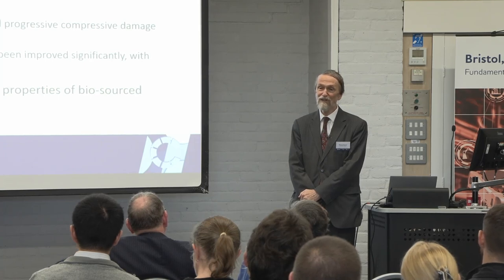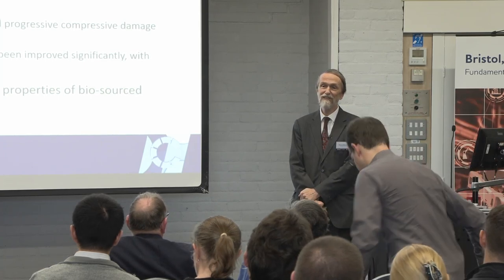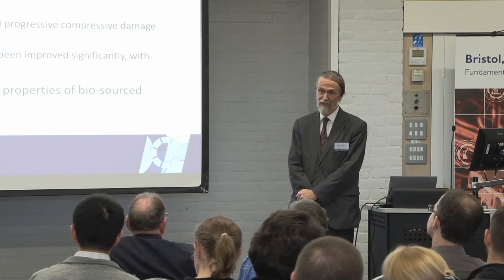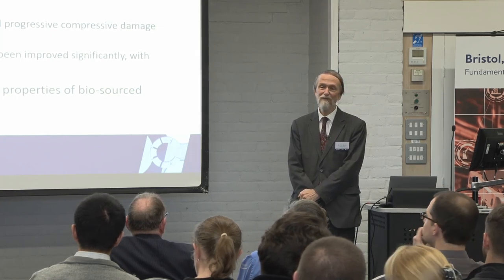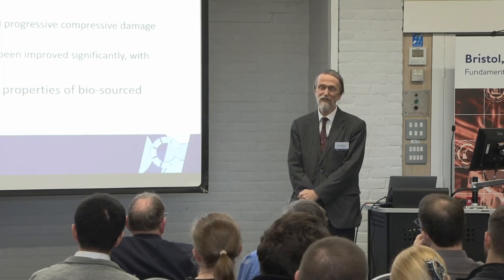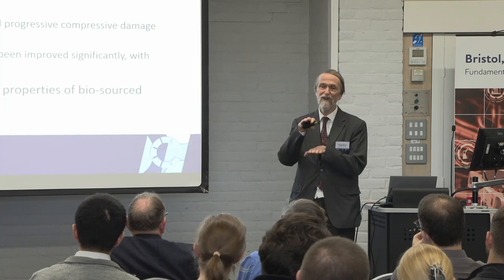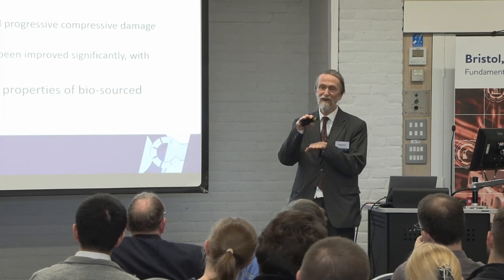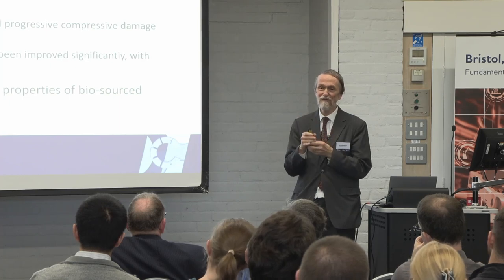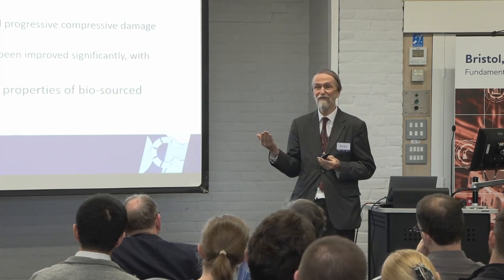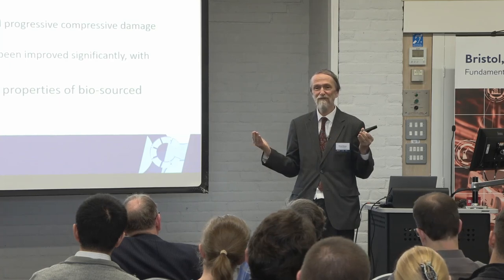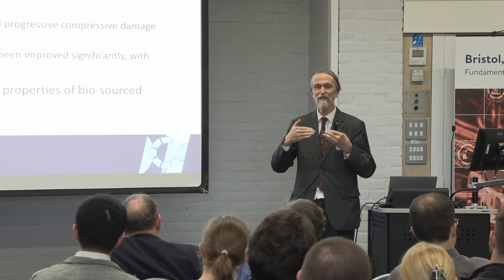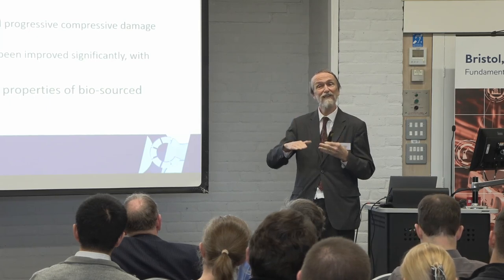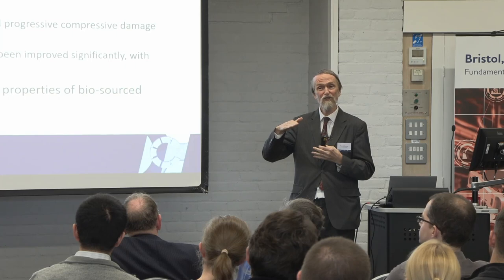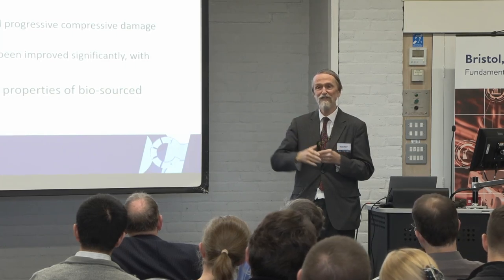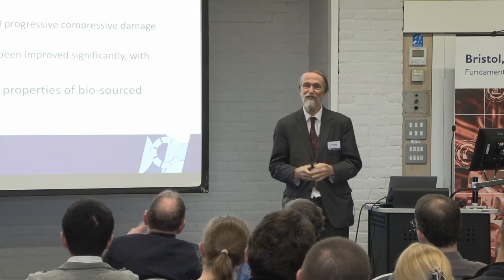So I think that's a really interesting point, and I think that would be an excellent thing to do. In this particular project, we didn't do that, and the reason was because one of the criteria we had to achieve was to not have any failure on the surfaces. Now, when you put a high elongation material, some of the materials such as Dyneema, for example, wonderful in tension, but very poor in compression. So if you have it on the surface, then you'll see damage on the surface. If it's inside the laminate, you might be able to control that, but without having surface damage, which our partners did not want to see.